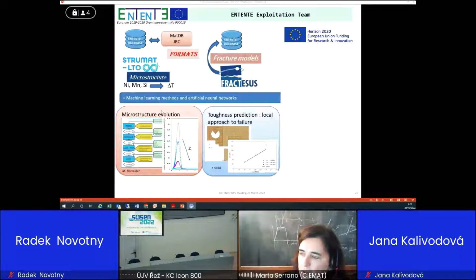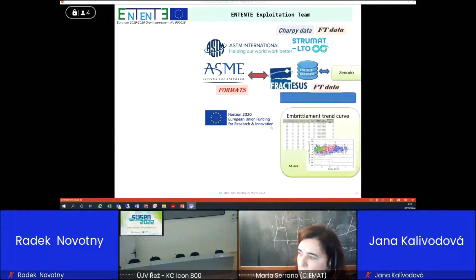STRUMAT-LTO, we can use STRUMAT-LTO data. STRUMAT-LTO deals with the variation of nickel, manganese, and silicon on the transition temperature shift. We can use this part of the exploitation, the Soteria platform, to analyze the microstructural evolution. In Fractesus, they deal with the determination of fracture toughness of irradiated material, which can also be supported by fracture models. And if we go up to an engineering level, the embrittlement trend curve, we have identified several international collaborations, but also Fractesus and STRUMAT-LTO, where they are producing fracture toughness data that can also be stored in the Entente database.